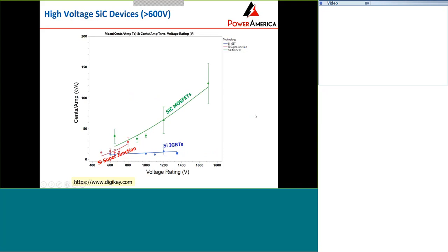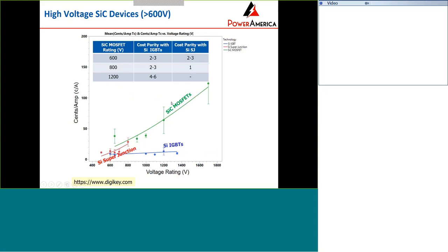On the silicon carbide side, if we compare the silicon carbide MOSFET with silicon superjunction and silicon IGBT, as shown in this figure, you will see that the silicon carbide MOSFET price is very close to silicon superjunction in the 600 to 800 volts range. But silicon carbide MOSFETs are still more expensive than silicon IGBT, especially as the voltage rating increases. This table compares the cost parity to the silicon IGBT. You see that at low voltage it is 2-3 times more expensive, and at 1200 volts even higher.